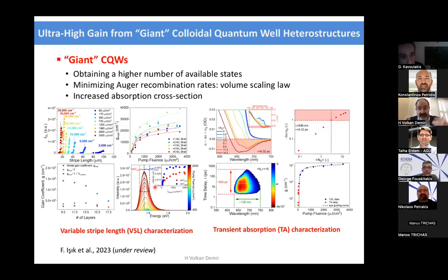And with that idea, just coming to our most recent work, we have been combining these two strategies, colloidal quantum wells, quasi-two-dimensional, make it laterally large, but at the same time, make it giant. So here we are pushing extremely thick wells, relatively, for what we can do. And what we achieve now is using what we call these giant colloidal quantum wells. And in terms of volumes, these are several orders of magnitude larger as a whole volume, excitonic volume, compared to the so-called giant colloidal quantum dots. We can push the gain further and further. These numbers are extremely large and only possible with significantly increased shell. And these shells, you should remember, we actually coat everywhere. So with, for example, 5 monolayers of shell coating, we are actually increasing to make it 10 monolayers additional coating.